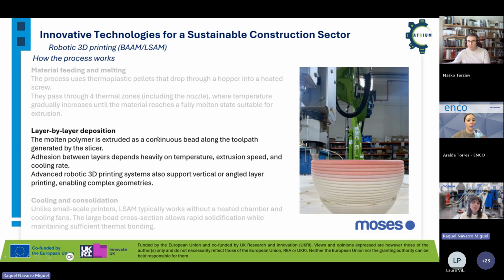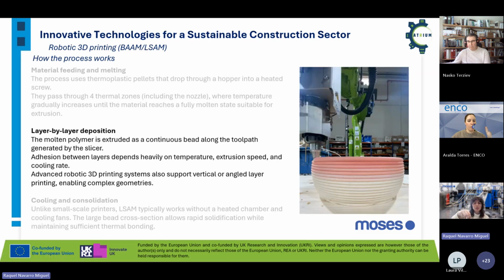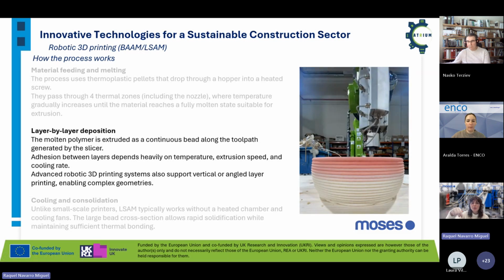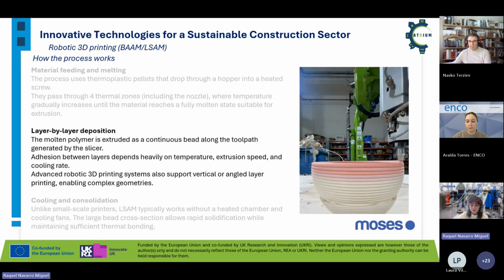This is the layer by layer deposition. The molten polymer is extruded as a continuous bead. Okay, so it follows the toolpath that we generated in the slicer. I'm going to explain later how we generate this toolpath, but in this process we are focusing on the adhesion between the layers, because it depends a lot on the temperature, the extrusion speed, and the cooling rate. And it's really important, because if you don't have a good adhesion between the layers, the part is not growing well, so you will not obtain the final part. This kind of robotic additive manufacturing lets us support vertical or angled layer printing, also enabling complex geometries. And this is the video.